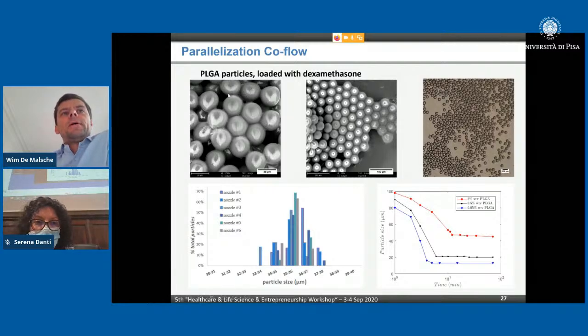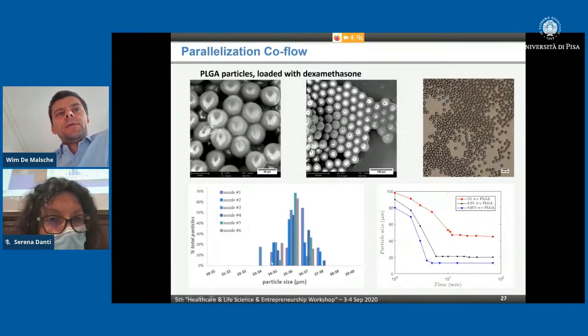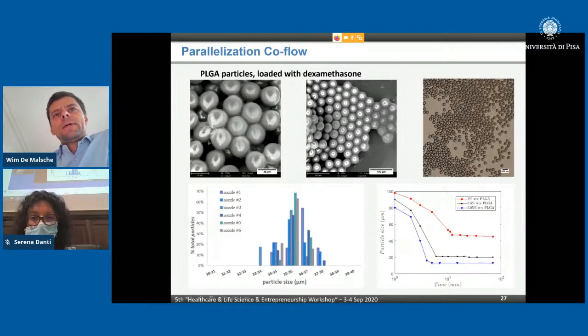Well, these images now are PLGA particles already loaded with dexamethasone. They changed a bit because of the sample prep for the SEM. But you can see here a typical size range from 33 micron to 38 micron, which is produced in 6 nozzles. It is a monodispersed sample, which is the type of sample that my collaborator needs to make the conclusions that she wants to make.